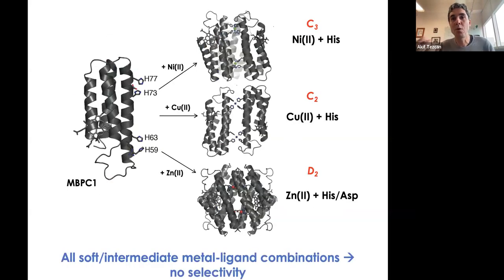The problem is one of selectivity, because both nickel and copper and the histidines are what we call soft or intermediate soft metal-ligand combinations. So that means there's no selectivity. If I add nickel 2+ and copper 2+ to this building block at the same time, I would just get a mess, because these histidines have no preference for nickel over copper 2+. So there's no selectivity, which proteins actually get through these non-covalent interfaces.